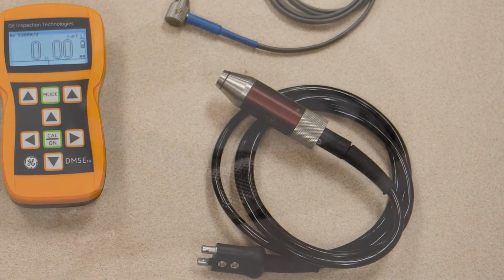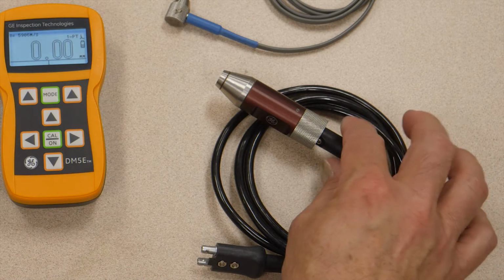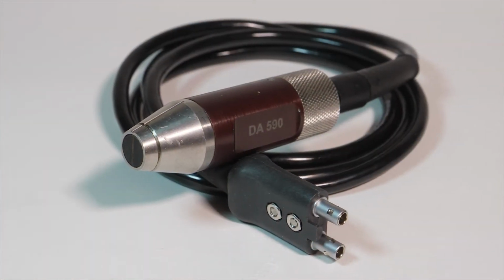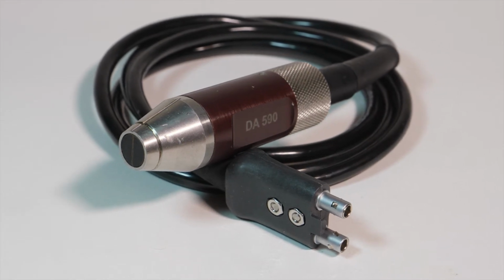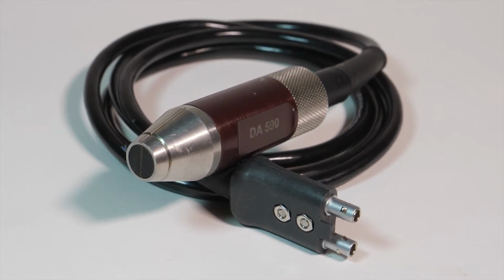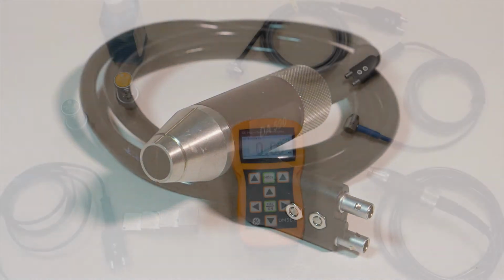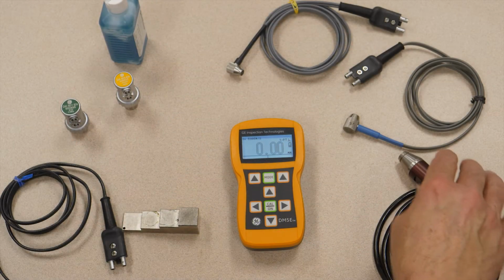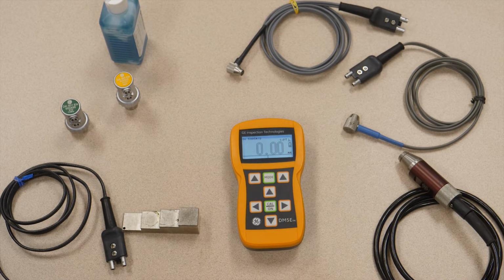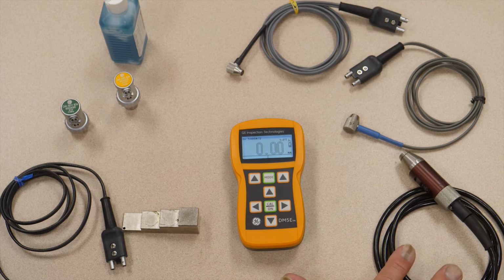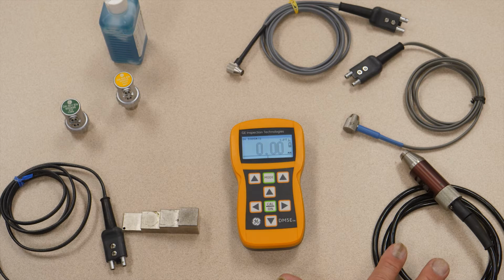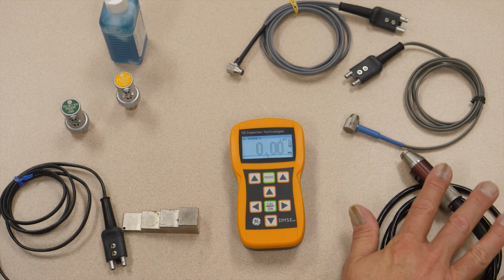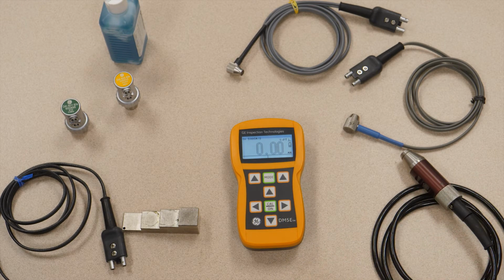And we also offer the DA590, which is a high temperature probe. You can measure on materials up to 400 degrees Fahrenheit with this probe. It's built to take the high temperatures. Now the DM5E, unlike the DMS-GO, our more advanced gauge, doesn't offer temperature compensation for the measurement. So you're still getting the raw thickness measurement, but the DA590 probe is available to work at higher temperatures.